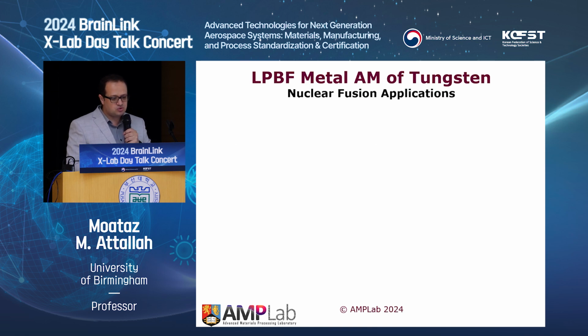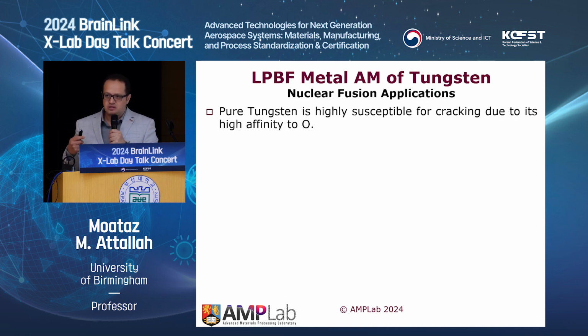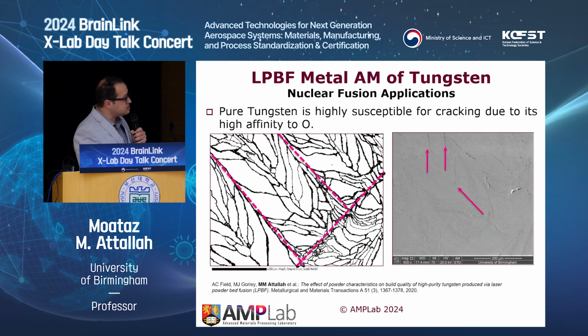So when we tried to print it, of course, tungsten with laser powder bed fusion is highly susceptible to cracking. It will suck in a lot of oxygen, so it always cracks. Even with the best practices, you're going to get some tiny little cracks in it, however hard we tried.